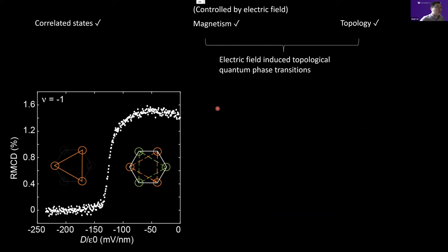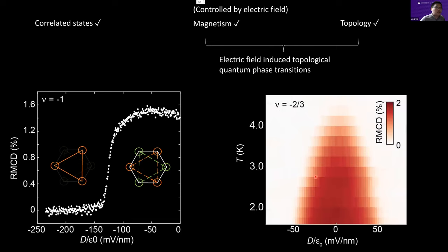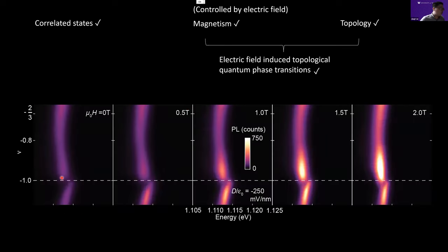Okay, so the next thing is to check the interplay of the magnetism and non-trivial topology of the system. What we previously proved is that the magnetism is controlled by the electric field. The hallmark of magnetism, the MCD signal, drops quickly if you turn the electric field from zero to negative. So you turn off the magnetism of the honeycomb lattice and transform it into a triangular lattice. It can also turn off the mechanism of the fractional states. So what will it do to the topological states? We can do the same measurement again to see how the fractional state disperses with the electric field, with respect to the magnetic field.